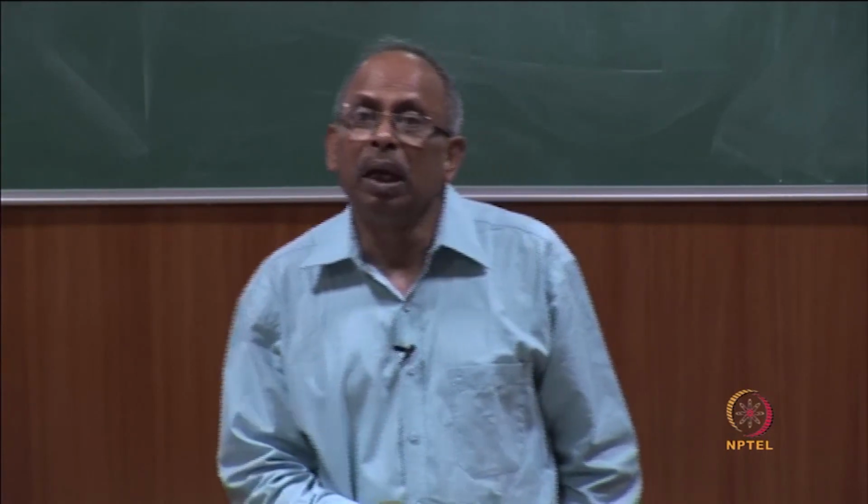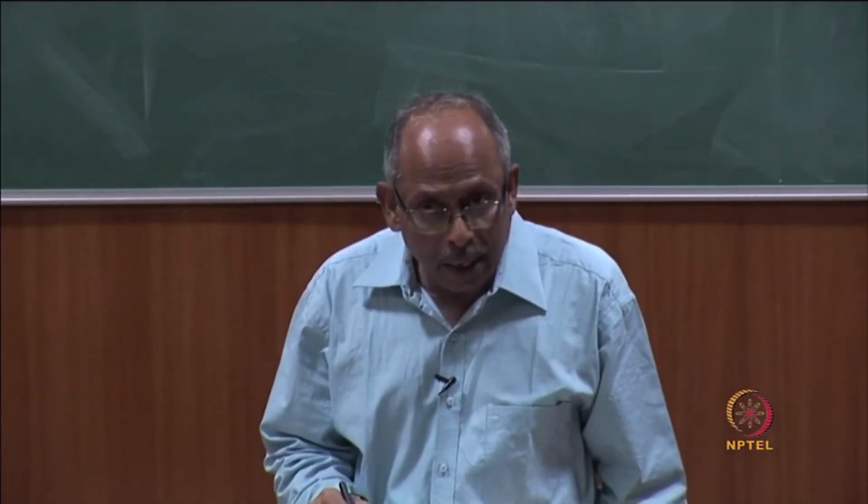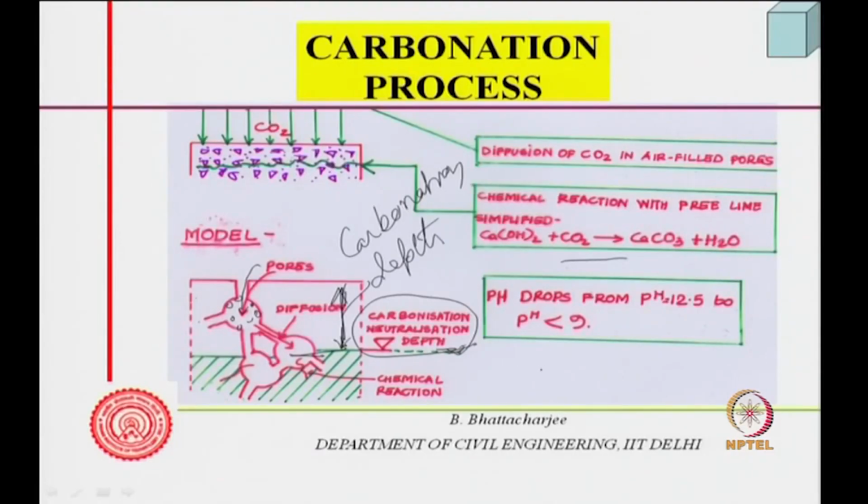In other words, carbonation is maximum at, let us say, 50 to 60% RH. At 100% RH it reduces down,